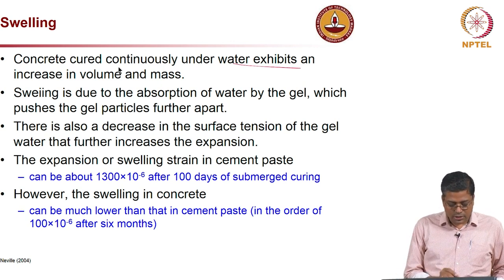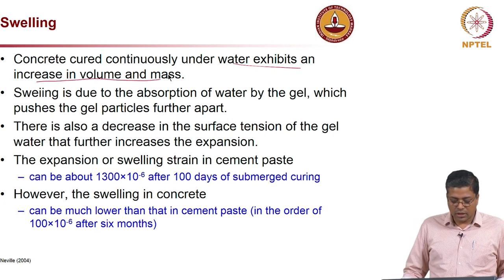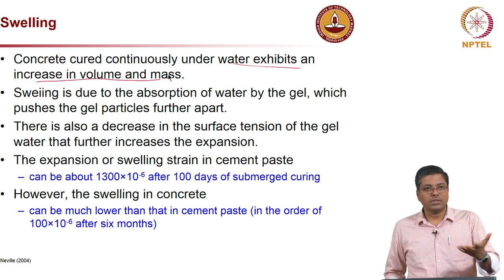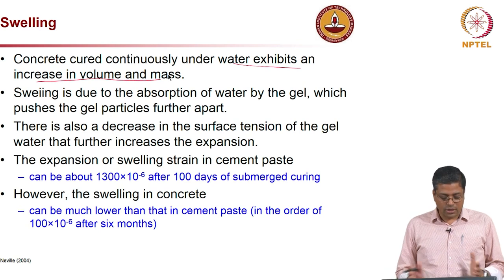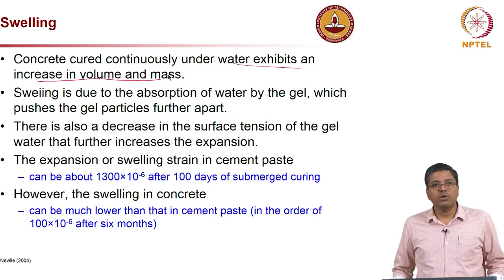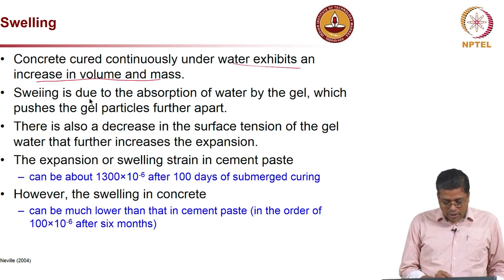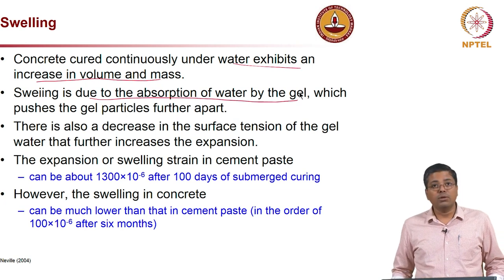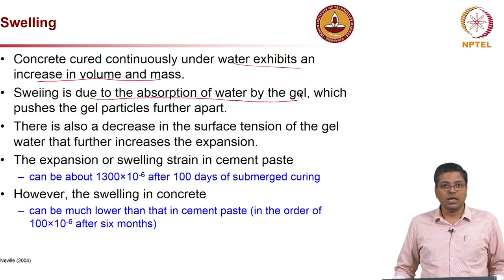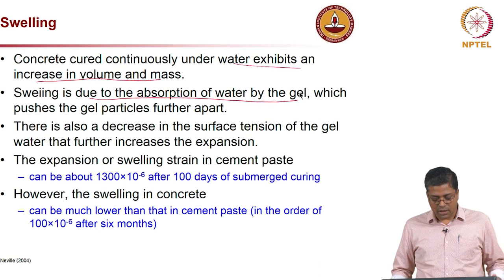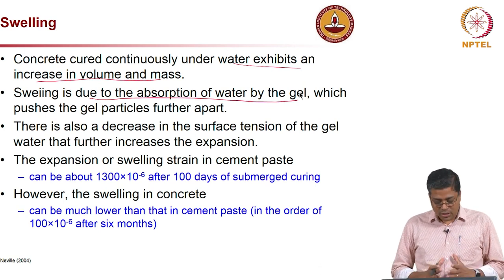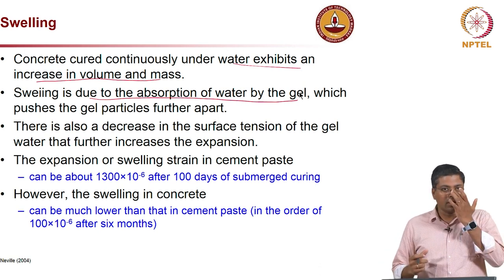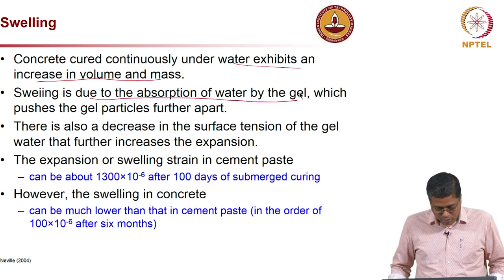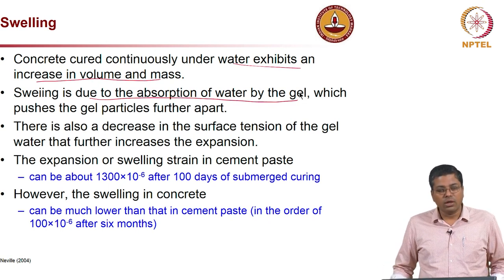So, the water exhibits an increase in... the water gets into the concrete, and then definitely there is an increase in the volume and mass. And why? Because of absorption of water by the CSH gel, which pushes the gel particles further apart, meaning the water gets absorbed and then it pushes, and eventually the volume of the concrete itself increases.